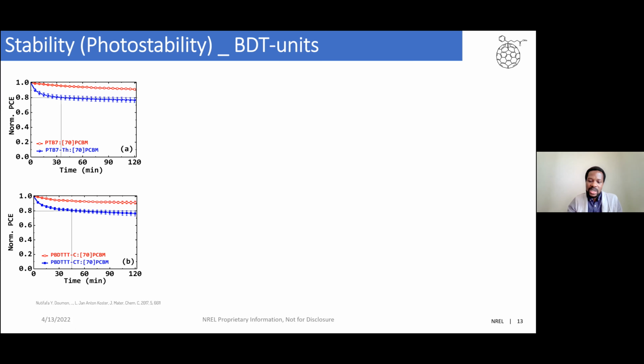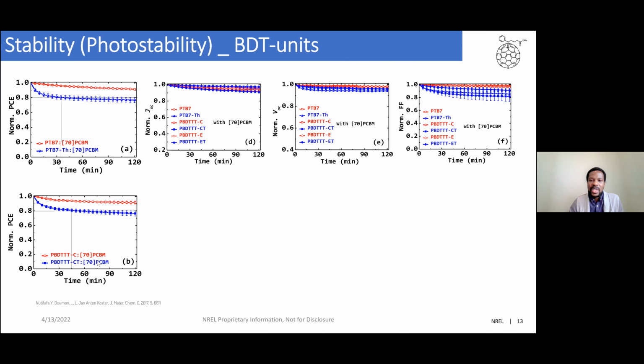And we try to look at this in detail, looking at the other JV parameters. And clearly here you can see that what causes this degradation is around the fill factor. Mostly the JSC and the VOC experience similar degradation rates under the UV stressor. Then the question becomes, how do you know that this is due to the polymer? Because this is what we're trying to assume. And because we also assume that the PC70BM, since the red and the blue polymer are from the same family, will act in a similar way, the effect of PC70BM should not be that much of a concern.